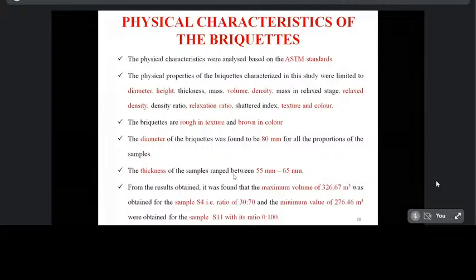So the thickness ranging between 55 to 65 mm is the main reason for the voids present in the particular mixed proportions. Okay. So from the results obtained, it was found that the maximum volume of 326.67 meter cube was obtained in the sample S4, and sample S11 attained the minimum value of 276.46 meter cube.